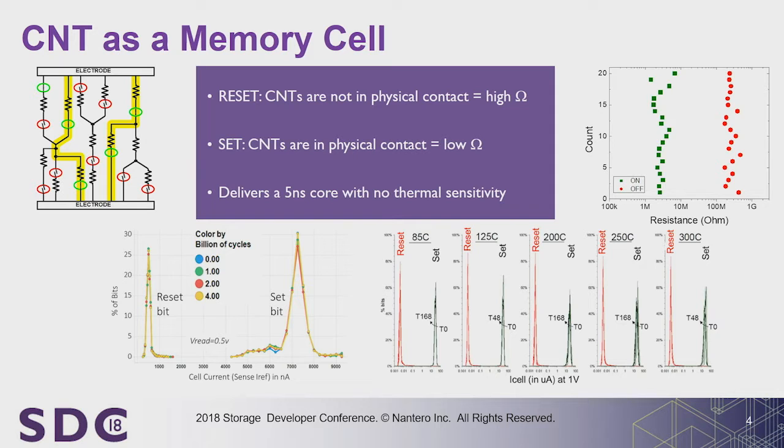of carbon nanotubes that are going to be wiggling around inside the cell, mechanically wiggling around and making contact and breaking contact. So the idea is that when you have a random array of these guys, you end up with this stochastic connection of a random number of tubes. And as long as we get a minimum of 100 tubes switching from connected to disconnected, we can detect that resistance change and do it in a way that's one setting for an entire boatload of wafers.